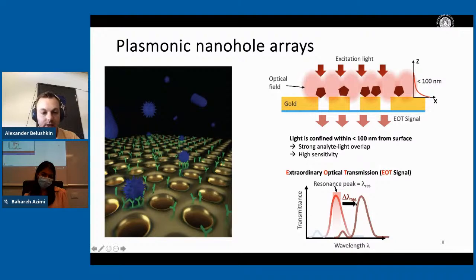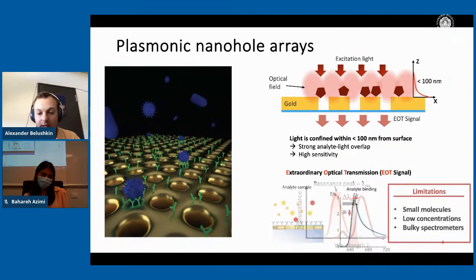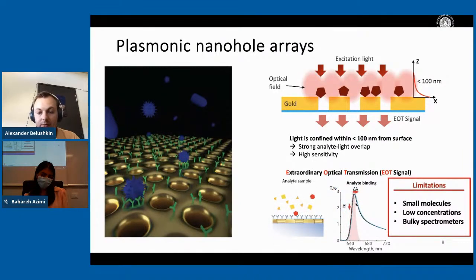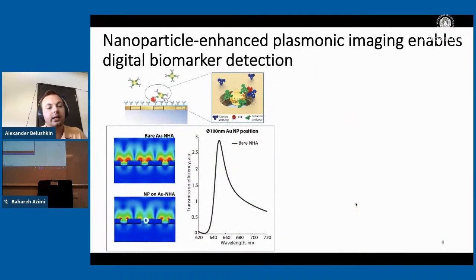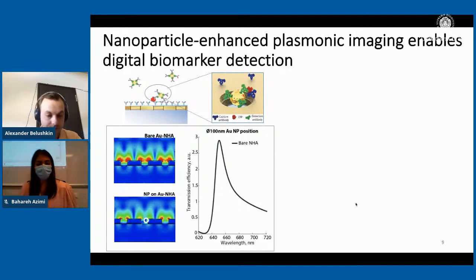The classical use case of gold nanohole arrays has been to detect in a label-free way. The problem with that, however, is when we want to detect very small molecules in very low concentrations from complex samples, we first of all need a large and bulky spectrometer, and second, we suffer from non-specific interactions from the serum or plasma of the sample we want to detect. That's why at the BIOS lab, we have come up with a so-called nanoparticle enhanced plasmonic imaging approach that essentially enables digital detection of individual biomarkers and individual molecules.